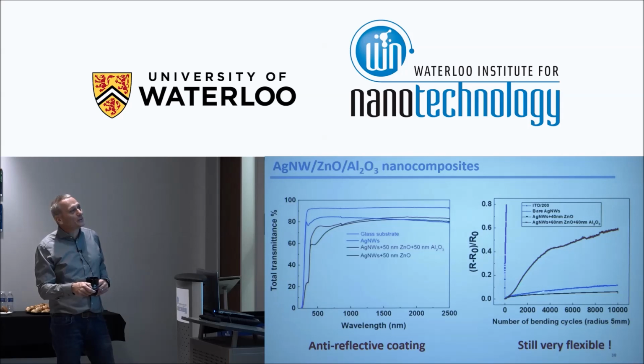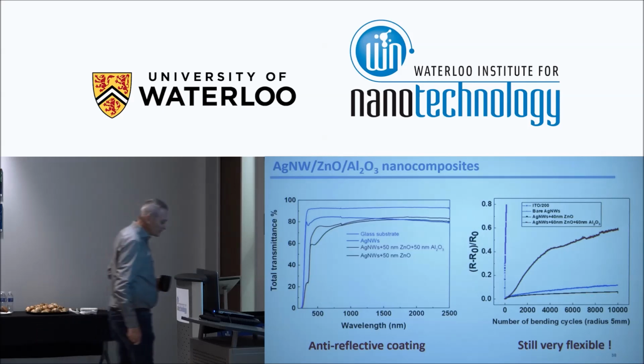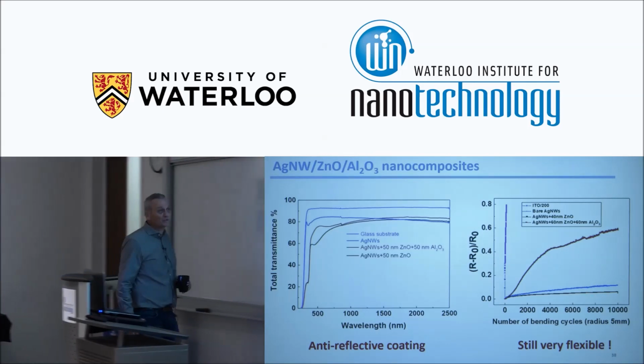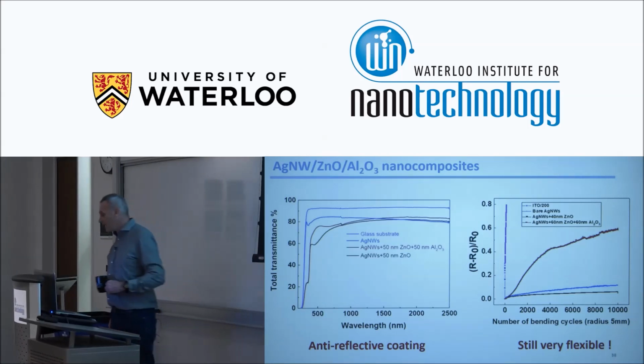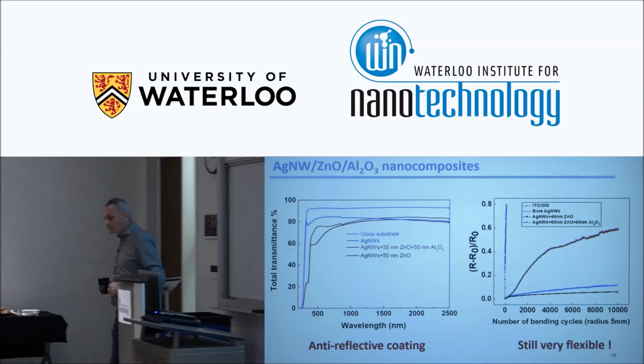For bare nanowires, we are here, okay? And this is silver nanowires with zinc oxide. And silver nanowires with alumina, we are even below the silver nanowires alone, okay? So we can find ways to put oxide to protect, to enhance the thermal or electrical stability of silver nanowires and making them still rather well flexible.